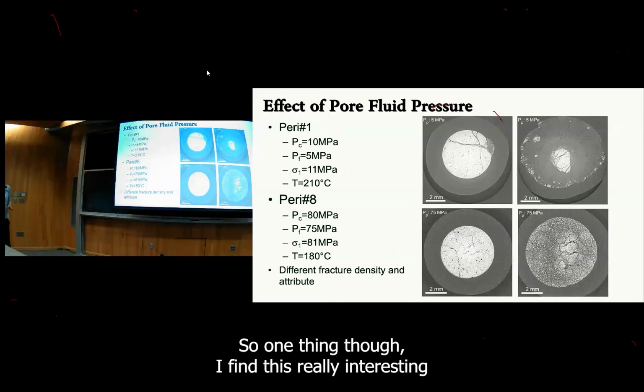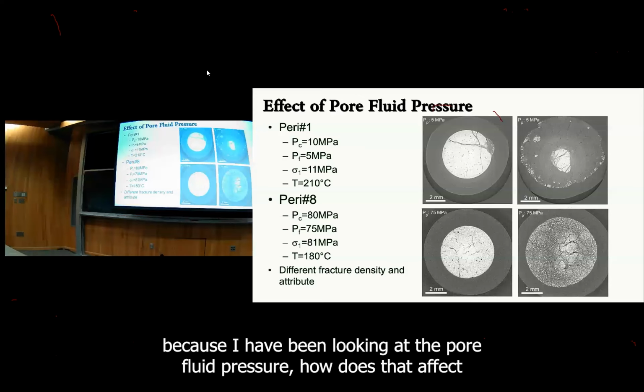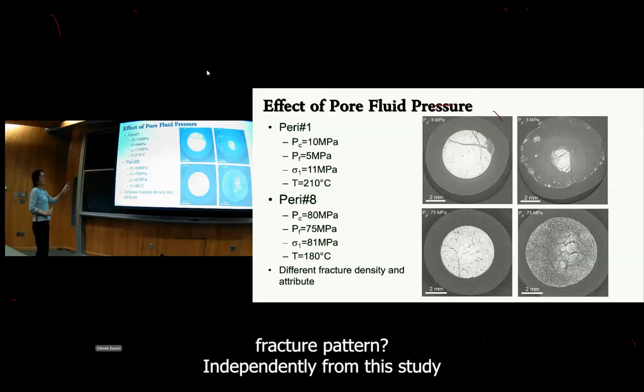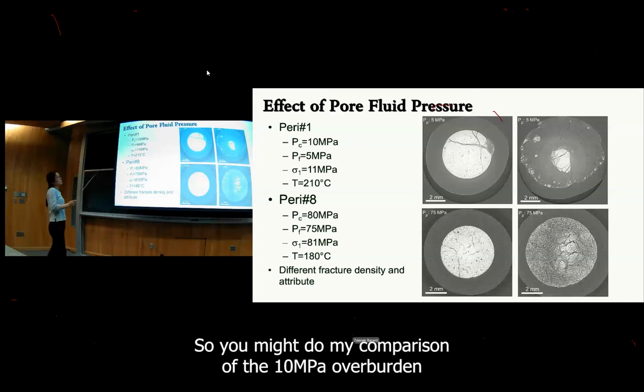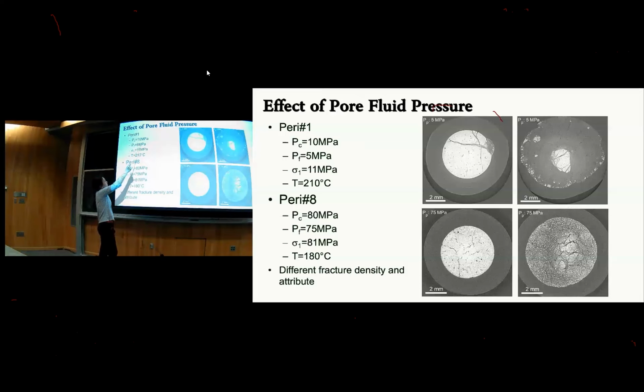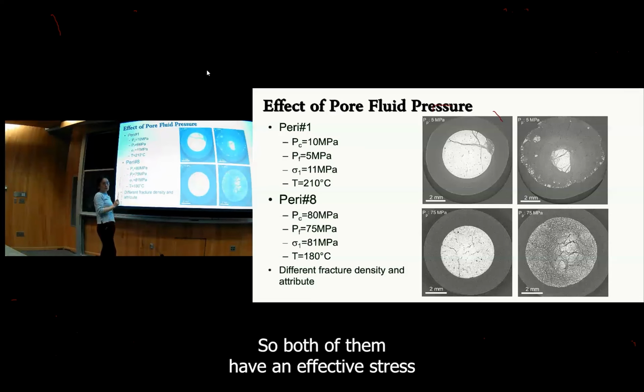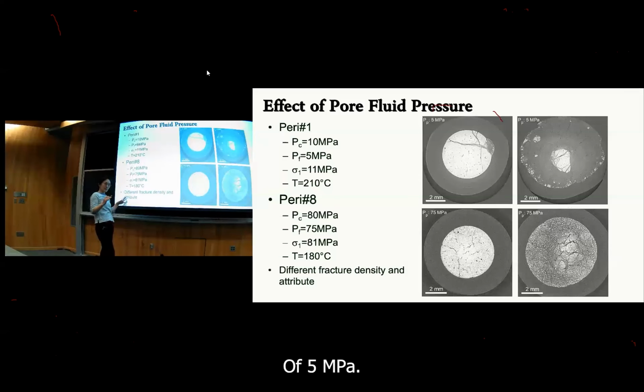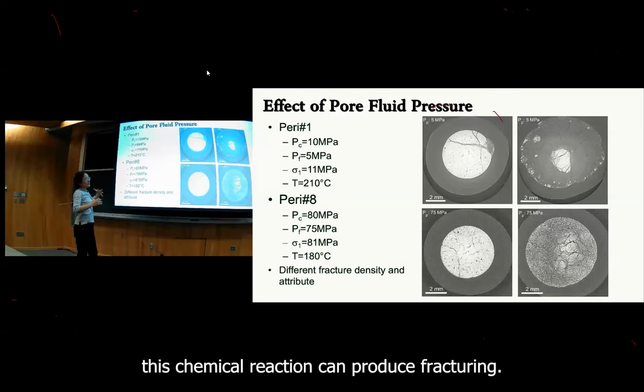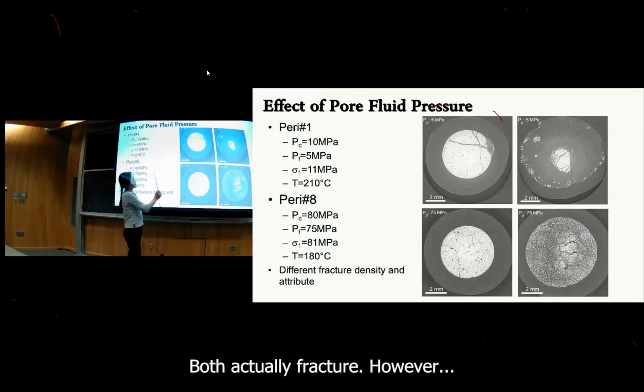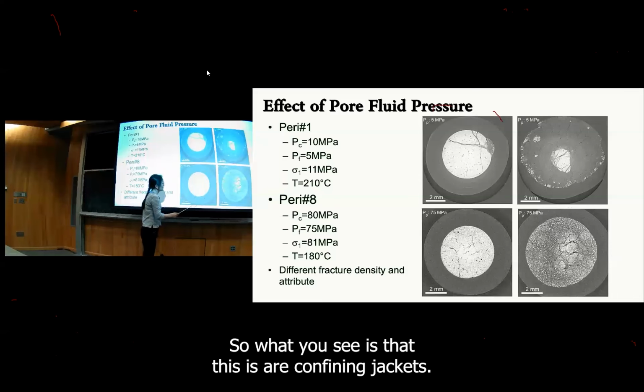So one thing I find really interesting, because I have been looking at the pore fluid pressure: how does that affect the fracture pattern independently from this study? So if I compare the 10 MPa overburden, 5 MPa fluid pressure versus 80 MPa confinement and 75 fluid pressure, both of them have an effective stress of 5 MPa. As I said, we find that below 30 MPa, this chemical reaction can produce fracturing. Both actually fractured.